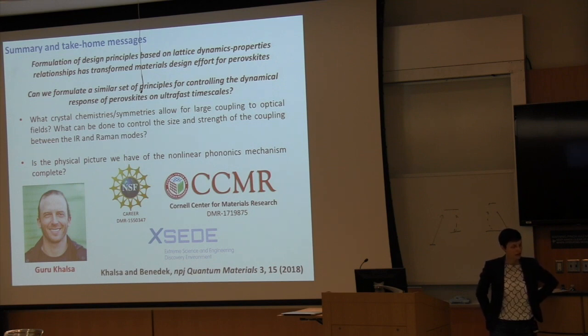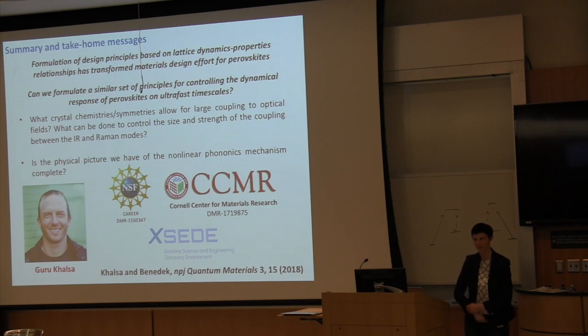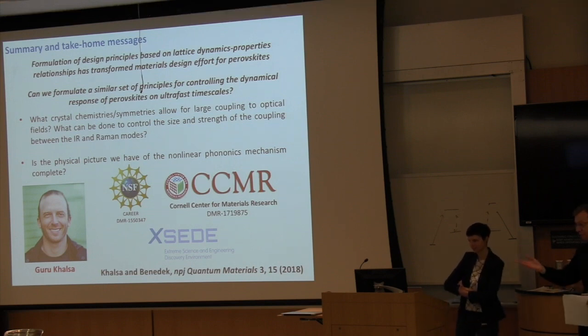So there are a number of Raman modes in play that span a range of frequencies, and the same with the IR mode. All modes that transform like the same irreducible representation as the excited one are coupled and will be excited. That frequency range is up to about 800 inverse centimeters. Okay, thank you.